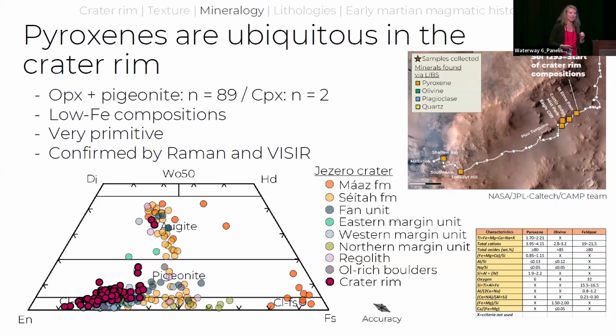And what's really cool about this campaign is we found a ton of pyroxene. And by a ton, I mean exactly 91 pyroxene, which is a lot, much more than what we found in the different campaigns. So hopefully you can see on the map in the upper right, those little orange squares represent locations where the pyroxene have been found. If you're too far in the back, it's just that pyroxene have been pretty much found everywhere in the crater rim.